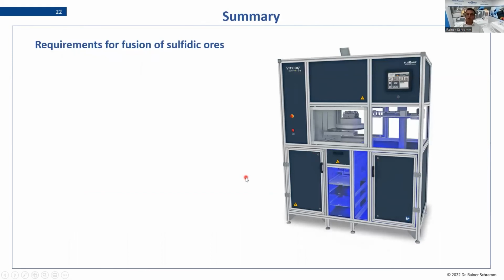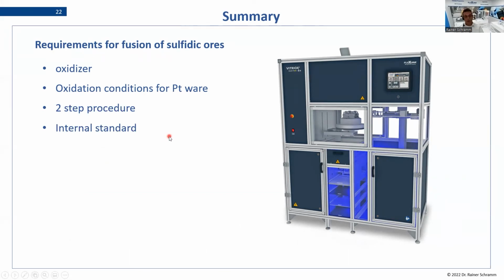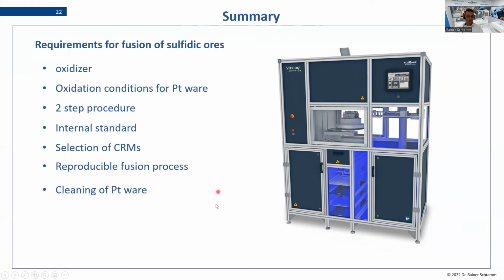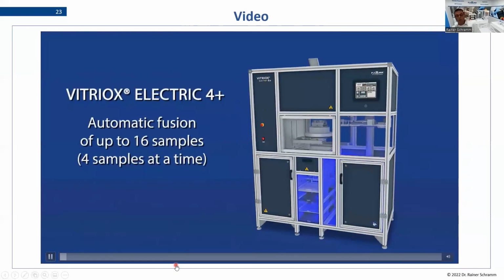Okay, let's summarize the whole application. So what we need is an oxidizer so that the sulfide is converted into sulfate, and there is no risk that the Platinumware is attacked. We have to make sure that the temperature for the oxidation is low enough. We use that two-step procedure so that we have no risk to destroy the platinum. We use the internal standard to have a longer use of the Platinumware. Then, of course, we need a selection of CRMs, and we need a reproducible fusion process. And of course, cleaning of Platinumware with memory effects also has to be taken into account. And now I wanted to show you a little bit how we do that in our laboratory.